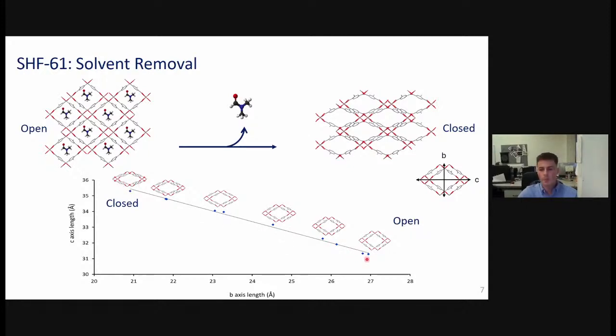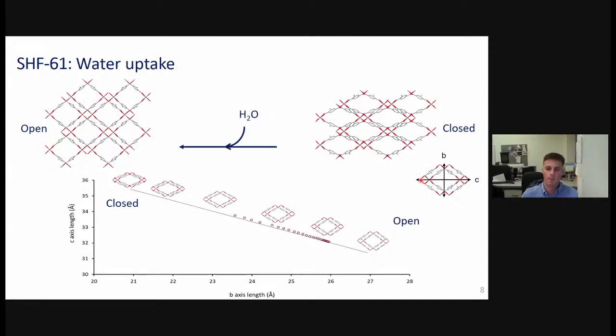Starting off here, we see the framework is open, so this is in its solvated state, and we have this continuum of structures to the point where the framework is closed and that solvent's been removed. We usually map these changes crystallographically by plotting the b and c axes, so those are the two dimensions associated with the pore width and length. This continuous breathing was shown to be fully reversible as well. If you start with our desolvated closed pore form and simply expose that framework to the atmosphere, the framework will absorb water and will undergo this gradual reopening of the framework.